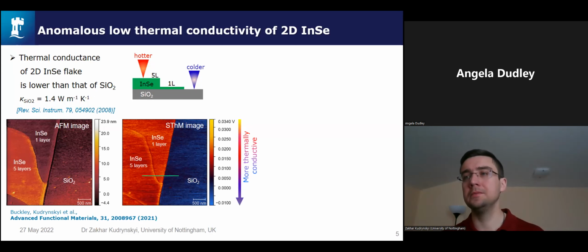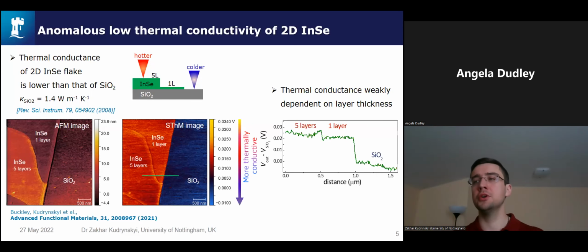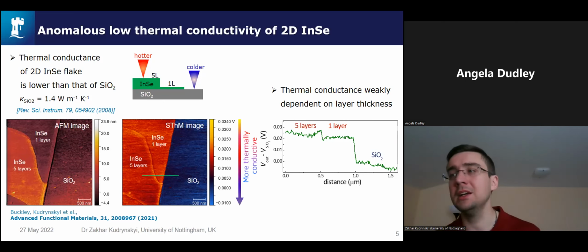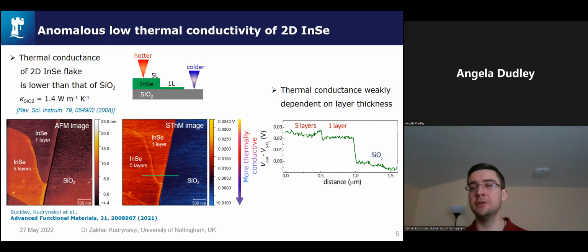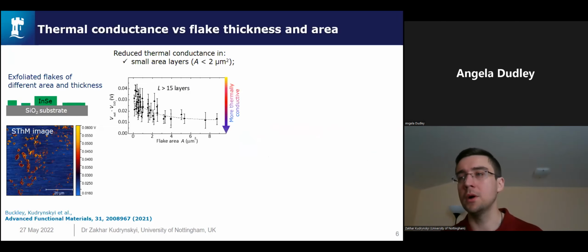And an SThM profile shown on the right illustrates the measurements done for 5-layer and single-layer parts of the flake, and reveals the thermal conductance. The thermal conductance only weakly depends on the layer thickness. I'll come back to the thickness dependence later in my talk.